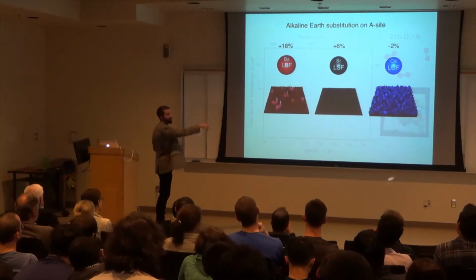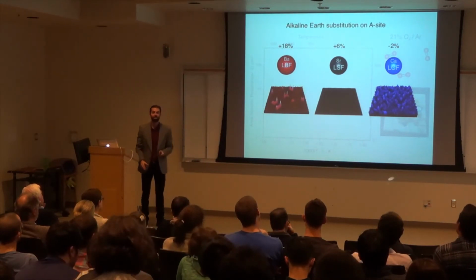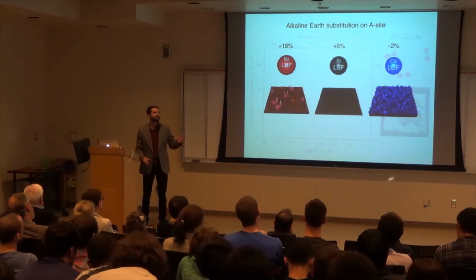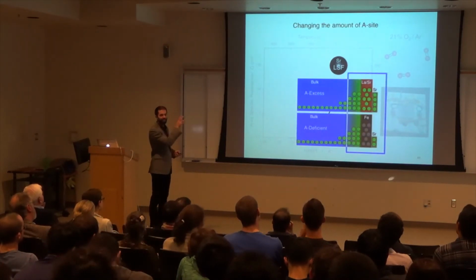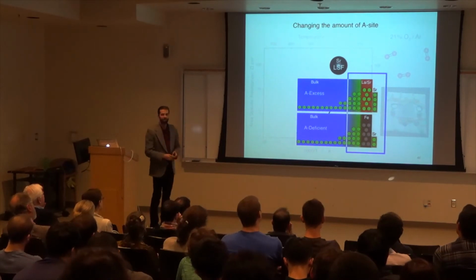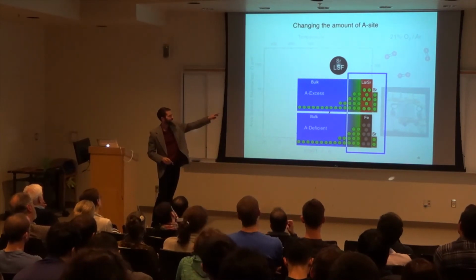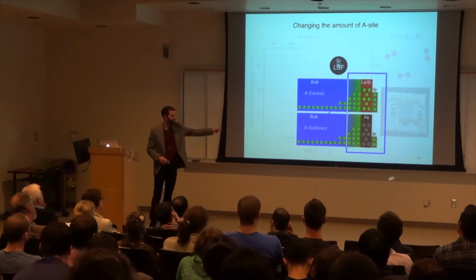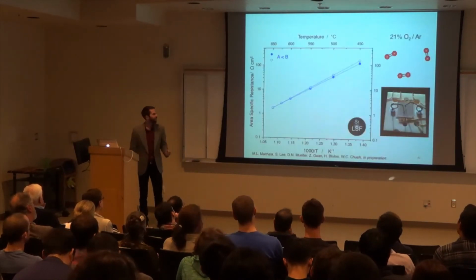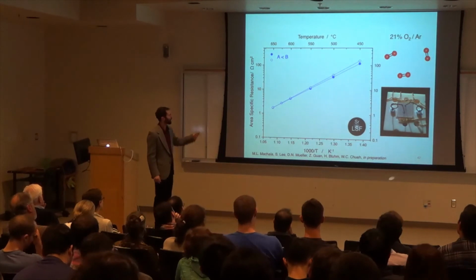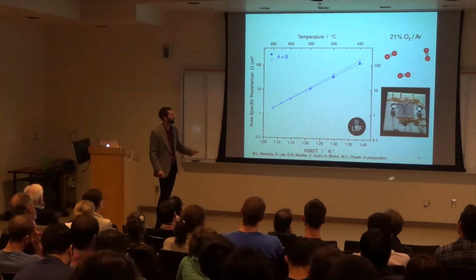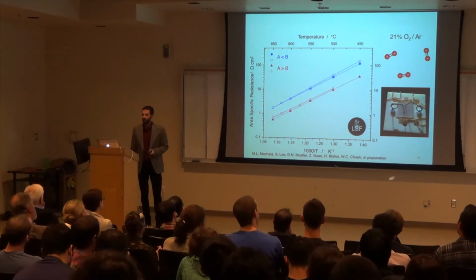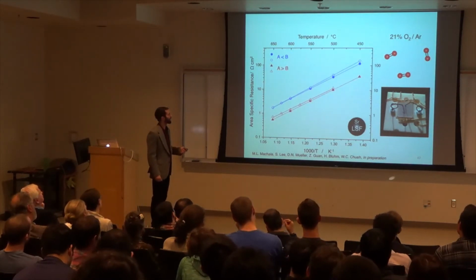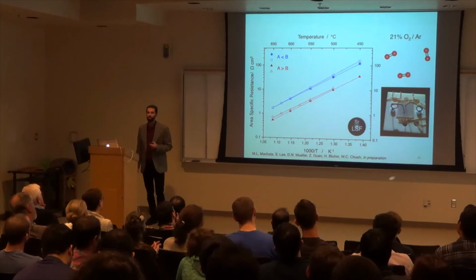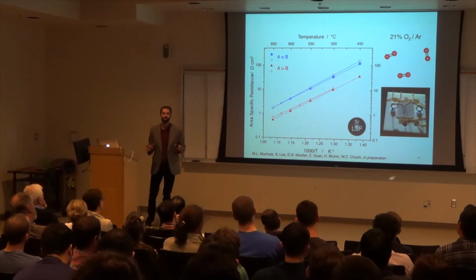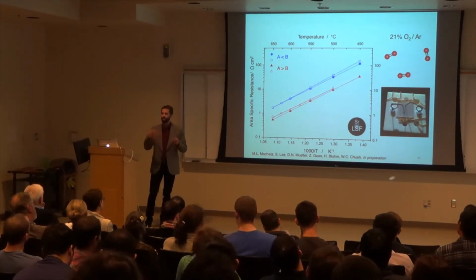So now we're going to focus in on the strontium again in the middle. And recall the measurements that we did to try to see if we put in a little bit more A-site or a little bit less A-site, what happens to the surfaces. We have these two different surfaces: A-site excess with A-site termination, and A-site deficient with B-site termination. Now here's the A-site deficient. If you might remember, it's a little bit higher than we saw previously. If you compare that to the A-site excess, we see that it's actually performing better, which surprised us, because conventionally, people only use A-site deficient in hopes that you're not going to get these precipitates.